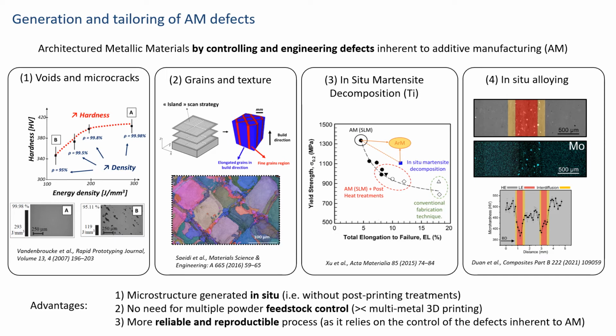Another strategy which is rather well known but has not been discussed in the context of architectures is to use a island scan strategy, for example, and this is well known to generate a bimodal distribution of grain. And also 2 strategies which are more related to titanium alloys are the in situ decomposition of martensite that could be used locally to create architectures, and also in situ alloying. So in this case, in a titanium molybdenum alloy, for example, by using different laser process parameters, you can or cannot introduce a lot of molybdenum in the matrix, and this allows you to create interfaces with a much lower hardness compared to the matrix.